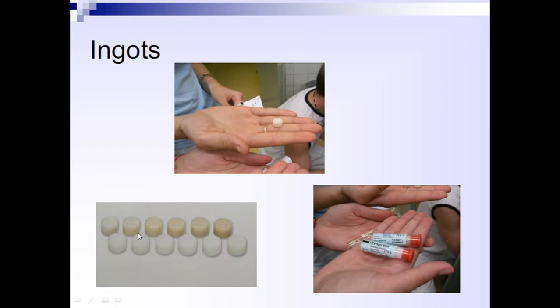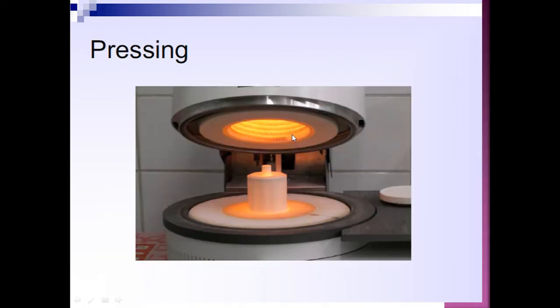According to the shade, we have different colors of ceramic pellets. We're going to put those ceramic pellets into this investment material, and because ceramic is a viscous liquid, more of a matrix kind of thing, we have to use a weight on top of the ceramic pellet, so that once the ceramic gets liquefied, because of this weight, the ceramic will flow into the ingot.